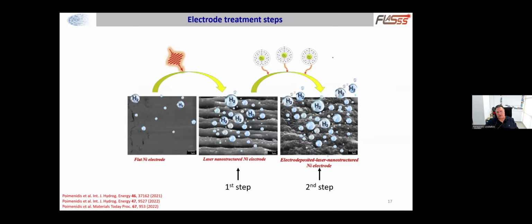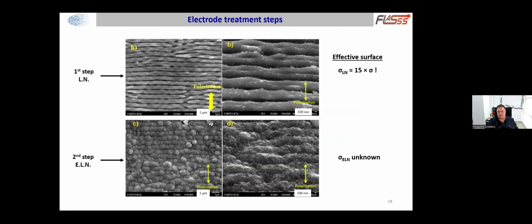Routinely, in our experiments, we prepare three kinds of samples. The first one on the left is traditional flat nickel electrodes, and we use them as reference electrodes. And also, we shine the laser beam on these electrodes, and we create ripple patterned electrodes as a first step of preparation. Additionally, as a second step of fabrication, we further electrodeposit nickel nanoparticles on these metallic electrodes. Let's have a look at how these samples look at the SEM microscope.